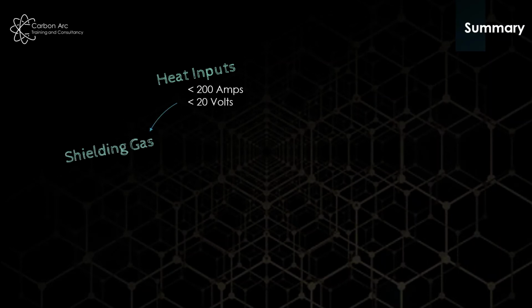So in summary, if we look at our heat input characteristics, we're beneath 200 amps, beneath 20 volts, low general heat inputs overall. For the shielding gas, we can use 100% CO2 shielding gases now, where in spray transfer we need at least 80% argon to create the spray process. Here we don't, because of course we're going to be hitting the electrode off the surface of the job, so cheap CO2 can be used now.